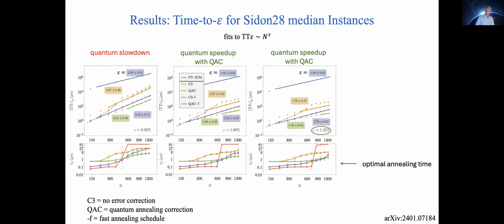And then if we go to an optimality gap of 1.25%, the situation improves even more. 1.16 versus 1.89. By the way, these are plus minus, these are 95% confidence intervals. And the C3 strategy is also beating PT-ICM.